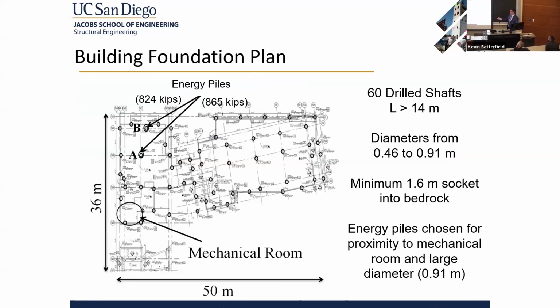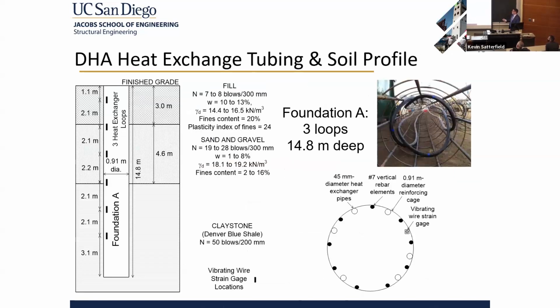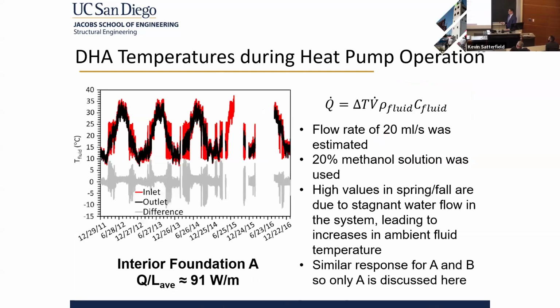We chose 2 different piles, A and B, to become energy piles, and we had to route the tubing over to the mechanical room here. These are larger diameter, about 1 meter diameter, and they go through this Denver blue shale, which we found was an interesting material that was sensitive to temperature. So these are just the operations of the energy pile with time. We looked at the heat transfer, and we got about 91 watts per meter, which is consistent with what I showed you in that graph before.